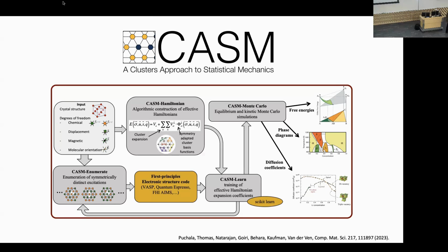And then what it does is it automates, spawns off, and enumerates different excitations, and sends them off to a DFT method, for example, a VASP code or Quantum Espresso. And then simultaneously, it algorithmically constructs these Hamiltonians using group theory of symmetry to clean it up. And then it does some training of the expansion coefficients using the DFT data, and then sends that off to a Monte Carlo code that's tailored for this particular Hamiltonian. And from that, you can calculate a variety of thermodynamic and kinetic properties.